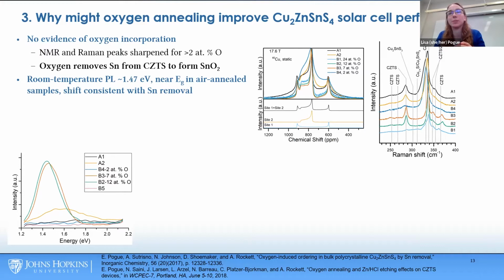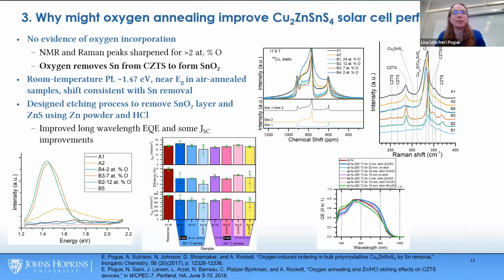potentially also some zinc sulfide at the interface between the buffer layer and the absorber layer of the solar cell, which should block current because both zinc sulfide and tin oxide are insulators. And so I then designed an etching process to remove the tin oxide and zinc sulfide layer using zinc powder and hydrochloric acid.